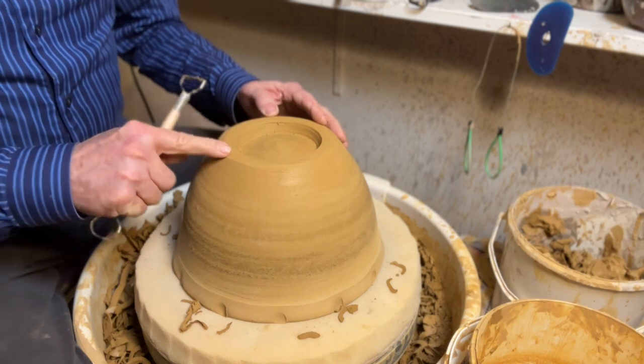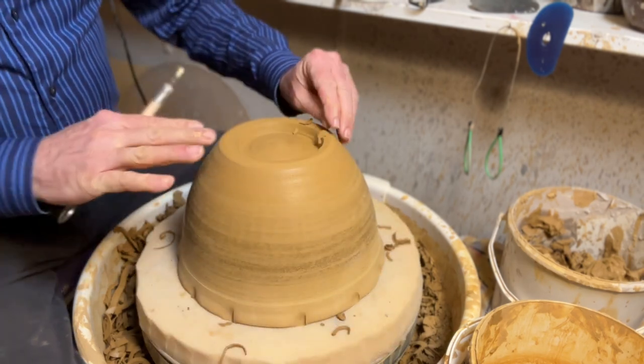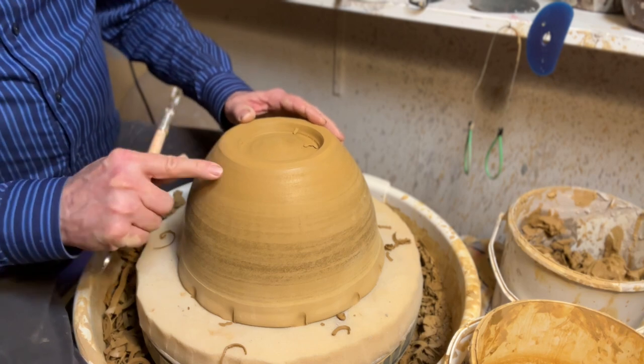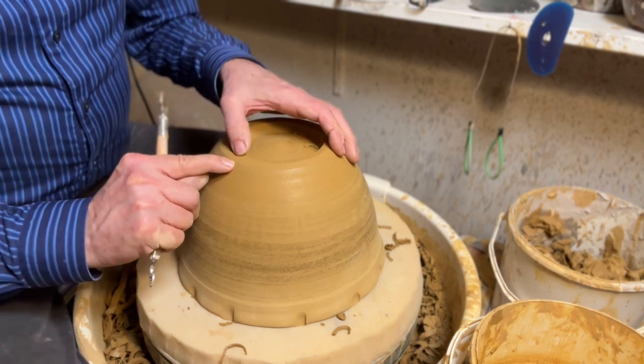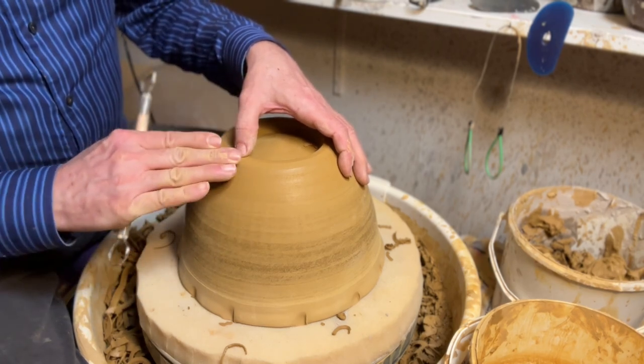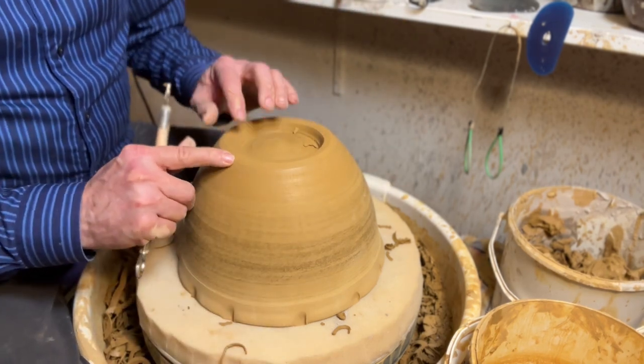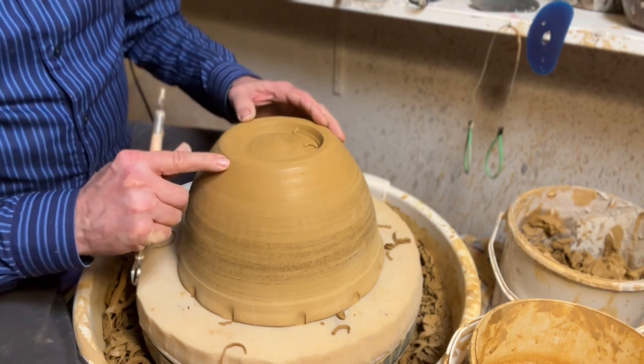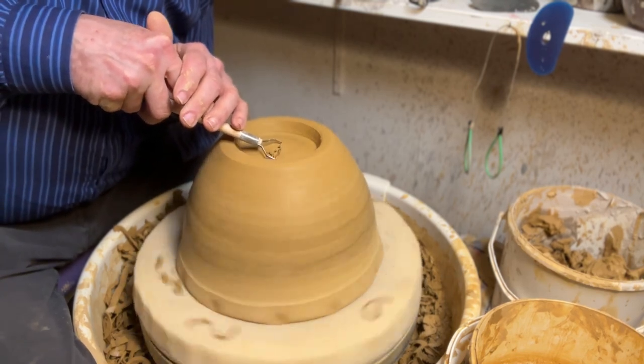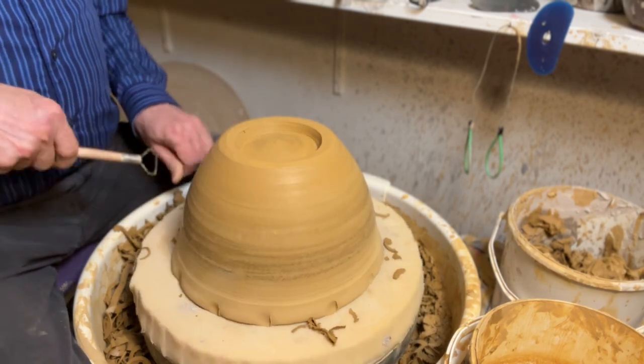I'm going to cut away a little bit here — only like a couple of millimeters, maybe half a centimeter or something like this. It's only visible from this side. So now I will only glaze to this part — there's going to be maybe four or five millimeters here that's not glazed, and it's got a 45 degree angle. When you turn this pot around, it's going to look like the glaze goes all the way down. But in reality it doesn't, so you don't have this problem of it sticking to your kiln shelf.